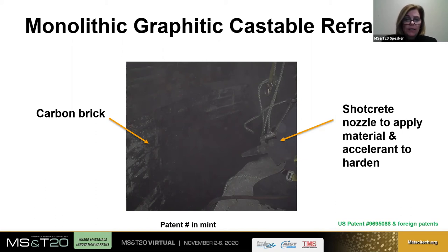If we look over to the image, we can see on the right, this is the shotcrete nozzle to apply the material, and accelerant comes through this and mixes with the refractory as it's applied to the wall. This is a wall of carbon brick. An interesting result from this work was that our R prime, our thermal shock factor, was actually better with this product than the original carbon brick.